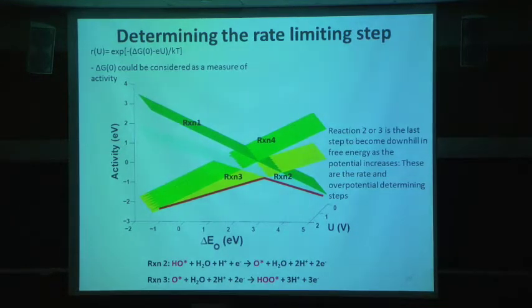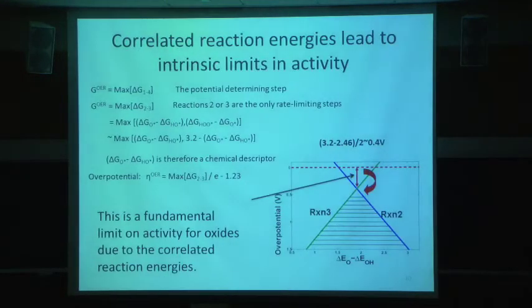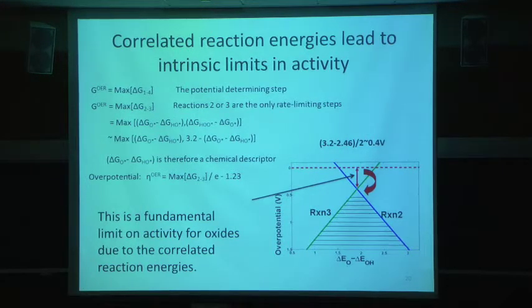Let's look at it a little bit more clearly. Over here you can see, again, we plot it now as the difference here, but reaction 3 is rate limiting for this class of materials, and reaction 2 is rate limiting for this class of materials. Now, that already is the origin of the volcano, that you have one rate limiting step on one side and another rate limiting step on the other side. So that is one reason why we have the volcano relation in the oxygen evolution reaction, is that we have a transition in rate determining step.